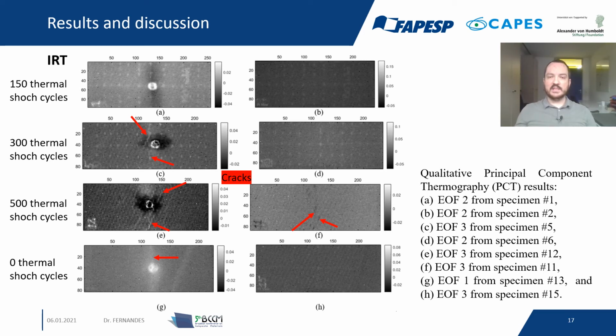Why is that? Because of the stress that this specimen was subject to due to the 500 thermal shock cycles, which could introduce some damage in the fiber and the matrix, causing some cracks. So because the specimen was cured in tension, it had some tension on it, and the thermal shock cycles cause some of this tension to be released, causing some cracks, and you can see that here, indicated by the red arrows.